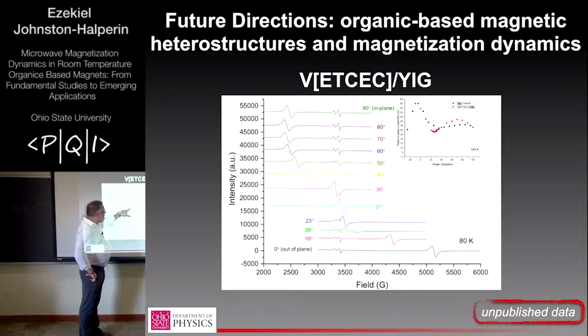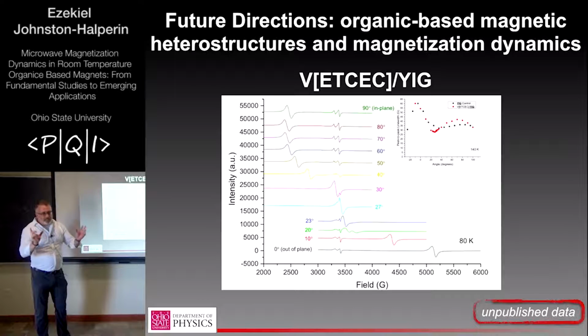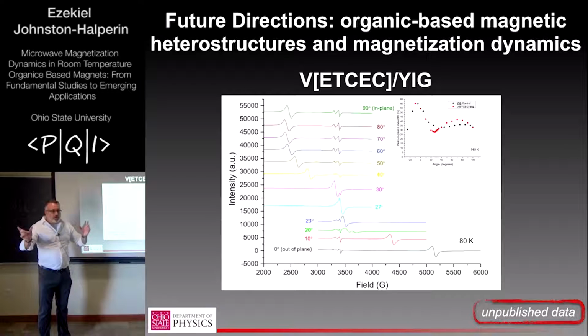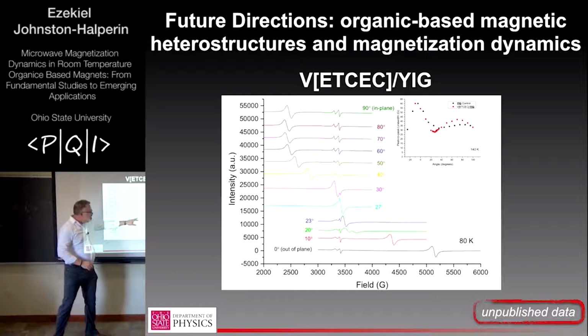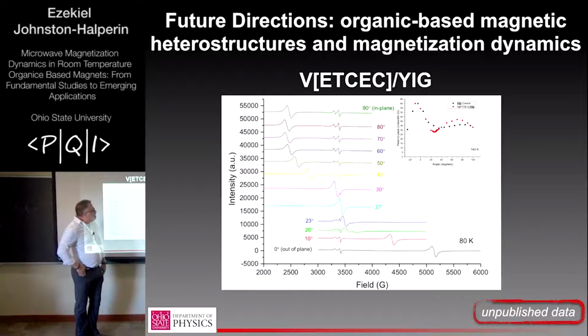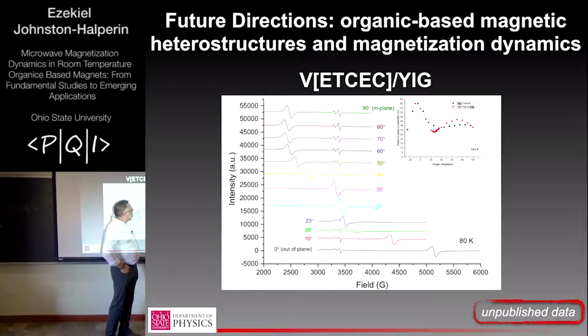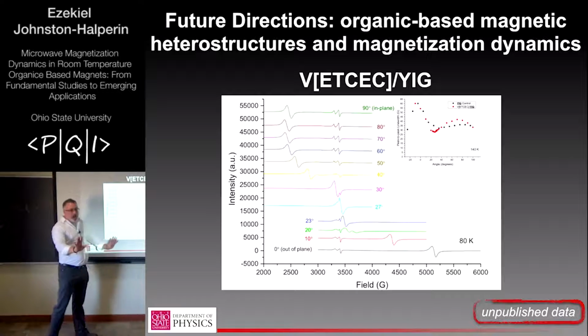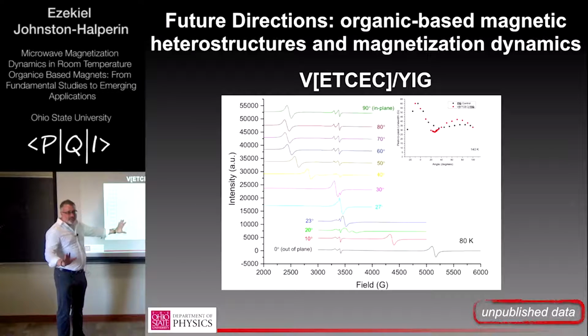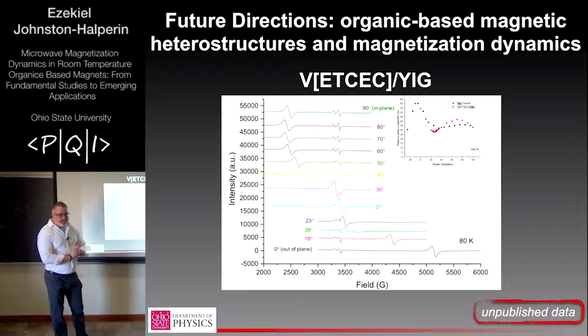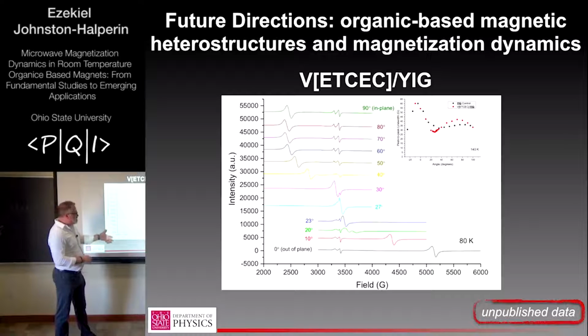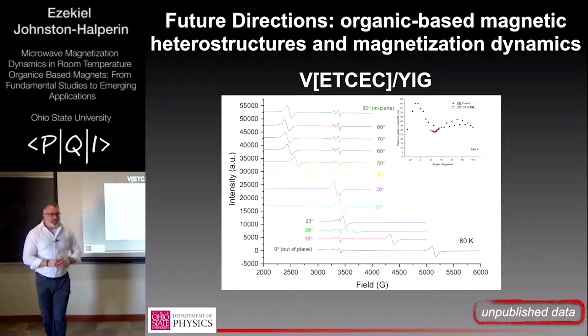I think they're starting to share oscillator amplitude. I think that's a generic effect if you have two coupled oscillators, right? As they couple, you get a common mode. And I think this is what's happening here. And so you can see there's a kink in the line width at about that field. So I won't say that this one plot is enough evidence to definitively say that this is happening. That's a fair statement. But it's pointing to some interesting potential.